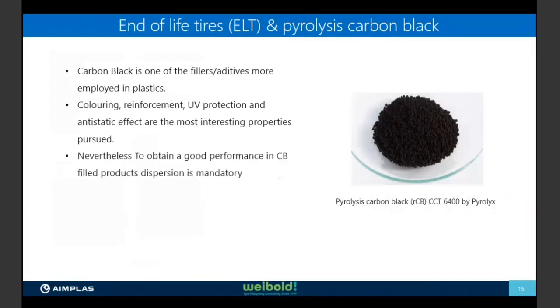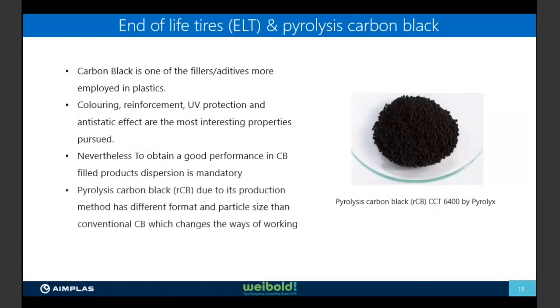But anyway, depending on the case, of course, we can obtain good properties, but it will depend strongly on the dispersion of this carbon black in the polymer matrix or in the rubber matrix. Otherwise, we are not going to have good properties. And at the same time, we need, for instance, to over-formulate, which is much more expensive. So in that study, what we did was to compare the performance of this recycled carbon black with commercial carbon black that we can have in the market. And what we did in the work that I'm going to show you right now is to compare the coloring capacity of both carbon blacks.